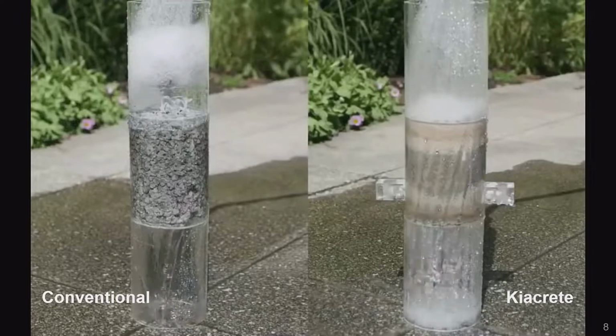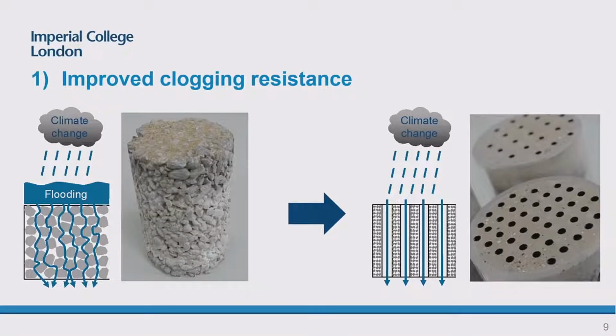of water almost indefinitely. The reason why that is the case is because the conventional permeable pavements have what we call a tortuous pore network. It means there is an indirect pore network. So if you get sediments blocking this section of the pavement, the rest of the pavement becomes completely impermeable. And when we try to maintain them, the maintenance only cleans the top couple of millimeters of the surface. So within a year, that becomes blocked up again, and then you need to clean it over time, and every year that requires that cleaning.